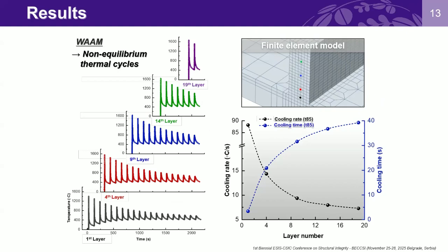Finally, the microstructural evolution mechanism is expected to be explained. However, as a general rule, the deposited layer always undergoes a high-frequency thermal cycle during the welding process, making the phase transformation sequence hard to figure out. To address it, a 3D finite element model was built. The thermal history was reviewed to assist the investigation of the microstructural evolution during the deposition process.